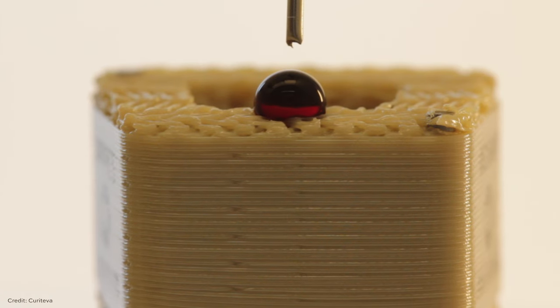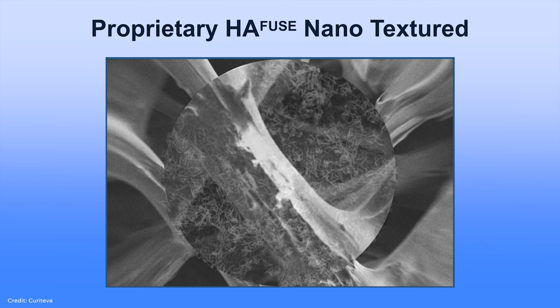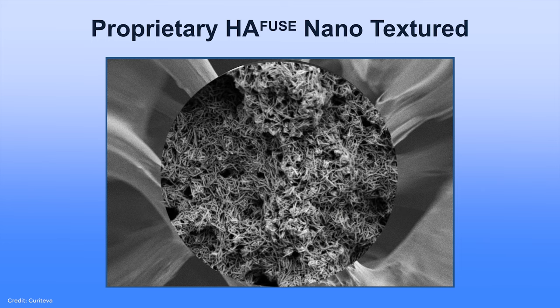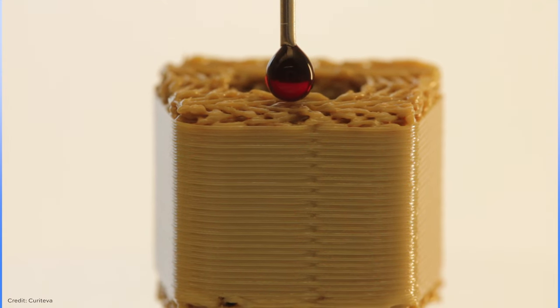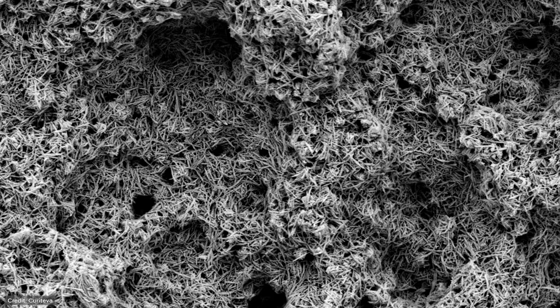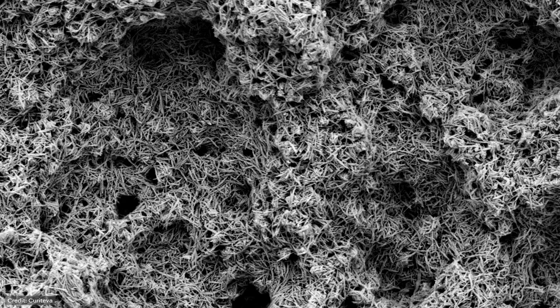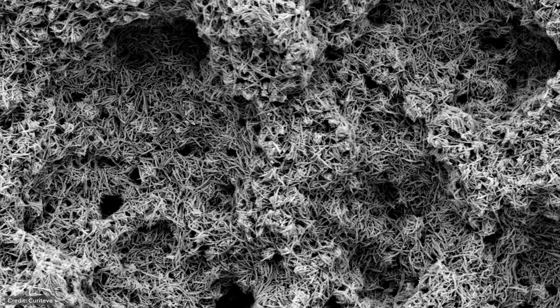The PEEK material is traditionally hydrophobic, meaning it repels, is not loving of water. To make it hydrophilic, one of the things we've done is to apply a nano coating of hydroxyapatite. This becomes important because this is done after we print the part. So it gets on every surface, every interstice, up in every single pore. That liquid is evaporated off, and then nano crystals of hydroxyapatite with the needle-like morphology are adhered very strongly to the surface of the implant, inside and out, all throughout. These nano hydroxyapatite crystals not only make it hydrophilic, but drive a reaction that forms bone that is known as osseointegration. So that coating is the way that Curiteva got around PEEK's hydrophobic properties.